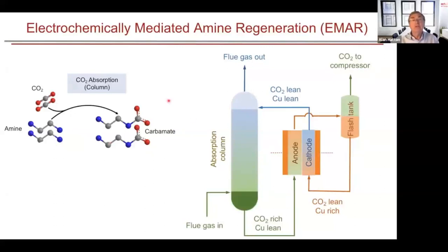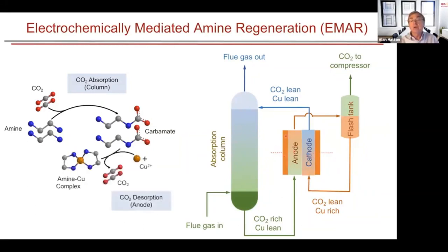We have an absorption column in which we absorb CO2. We have the amines coming in. The CO2 is then captured by the amines to form the carbamate. But the difference is the way in which we regenerate these amines. Instead of sending this to a thermally heated desorption column, we send this to an electrochemical cell, as shown here, where we've got these copper electrodes. And what we do is when you oxidize the copper electrode, we release the cupric ions, and these will complex with the amines very strongly, displacing the CO2. So CO2 comes off now as a pure stream, and we can then disengage that in the flash tank. Then this copper amine complex can now be taken back to the cathode chamber of the electrochemical cell, where we plate out the copper, and in so doing, we regenerate the amines, and can then be sent back to the absorption column.